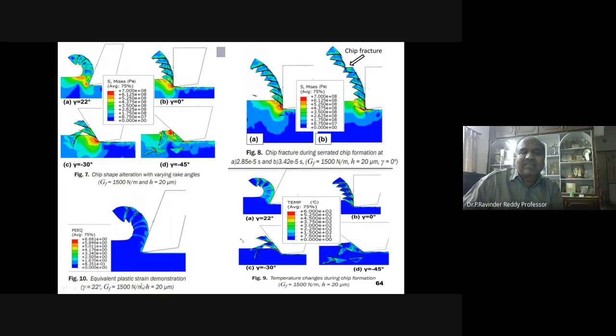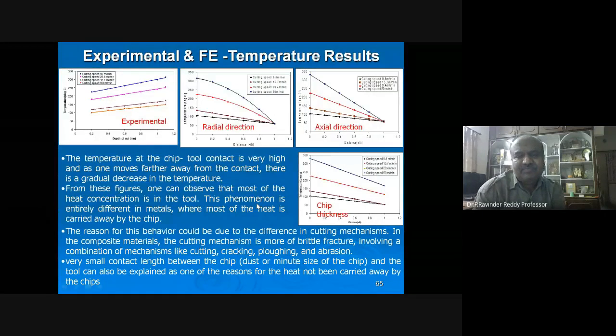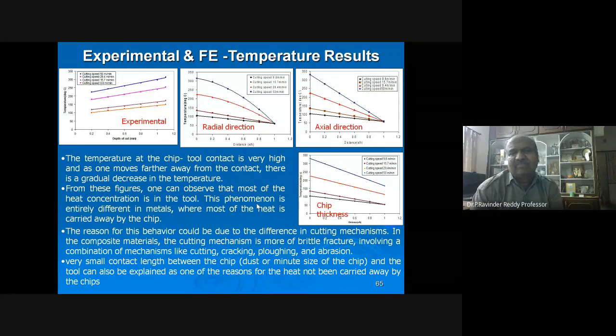And we can calculate the plastic strain, how the plastic strain is going to be. So this is the real behavior that is required. We can fix it and proceed further. And when you compare the results of both the experimental and the FE simulations, particularly the temperature distribution, we have plotted the temperature against the depth of cut.